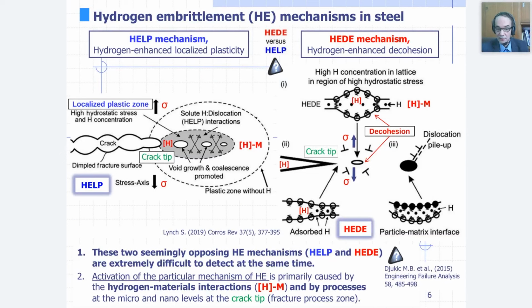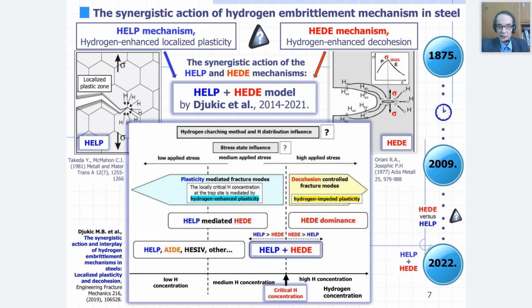These two mechanisms are extremely difficult to detect at the same time, so there are numerous papers which tell us about the HELP mechanism activity, about the HEDE mechanism activity, depending on experimental conditions and everything else. So, as a summary, activation of a particular hydrogen embrittlement mechanism is primarily caused by the very complex hydrogen-material interaction shown in the previous slide, and by the processes which are operative at micro and nano level at the crack tip, marked in green, exactly in the fracture process zone. So, HELP mechanism, on the other side we have a question mark, HEDE mechanism.